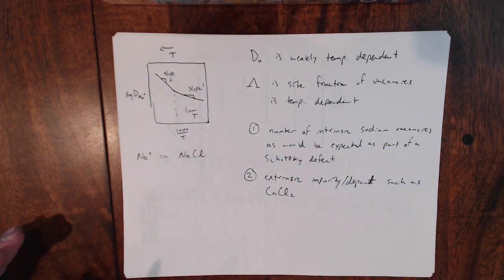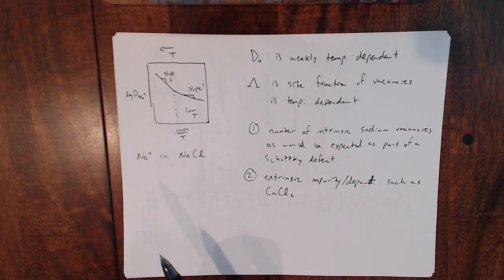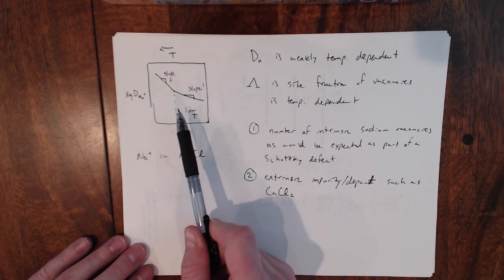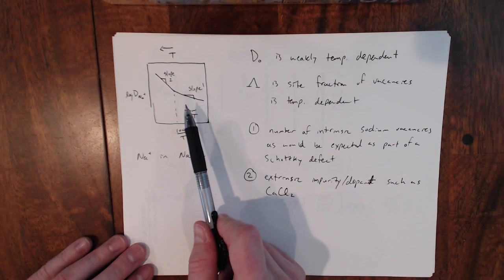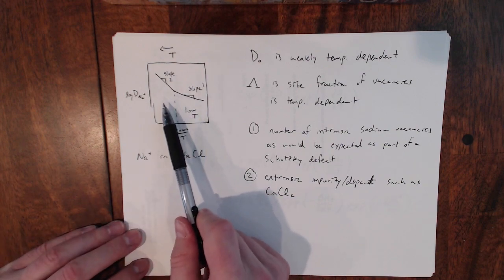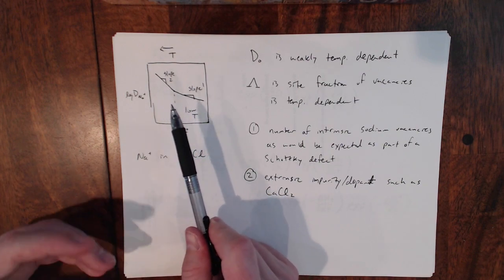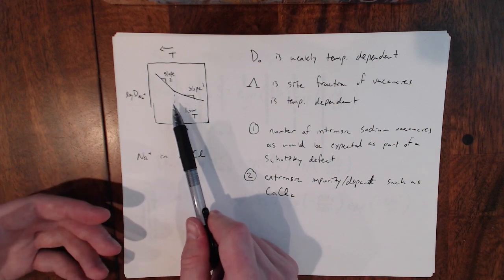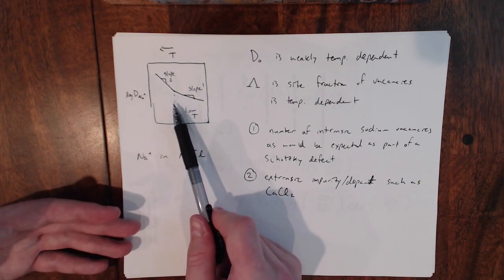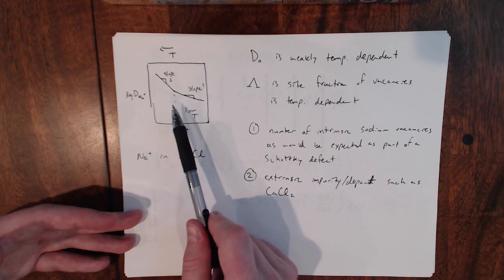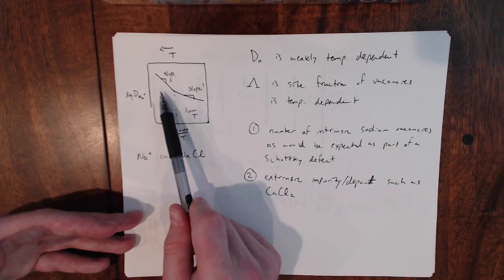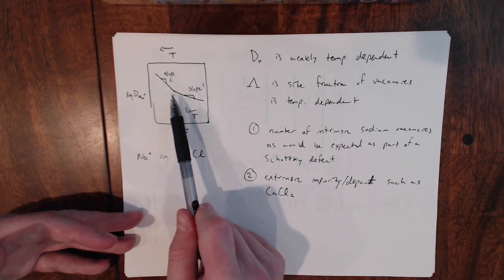So in the previous slide that I showed, where we had everything and it was all linear, those were very pure materials. But if we have real materials and they happen to have extrinsic doping or impurities, they may in fact have multiple slopes if that dopant and impurity affects the overall concentrations. And so that's kind of a deeper look at some of this temperature dependence that we can have. For the most part, it's linear. But again, if you are dealing with multiple mechanisms like extrinsic and then also thermally activated, you may have multiple slopes.